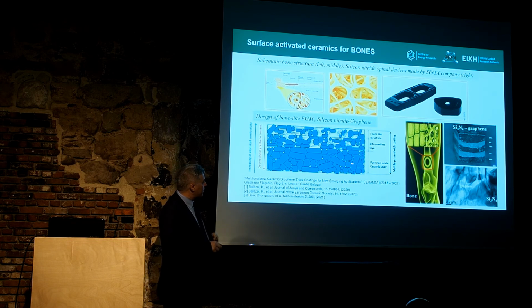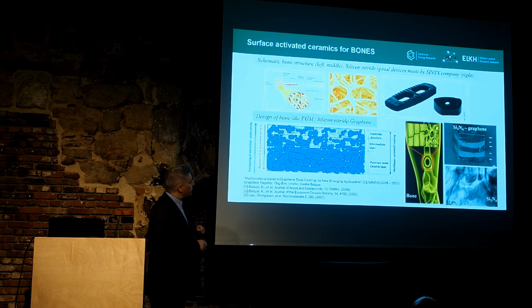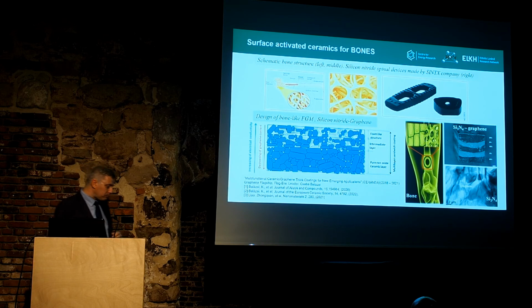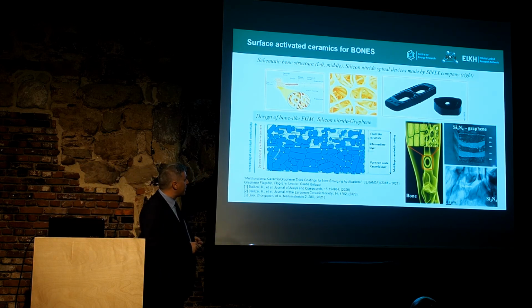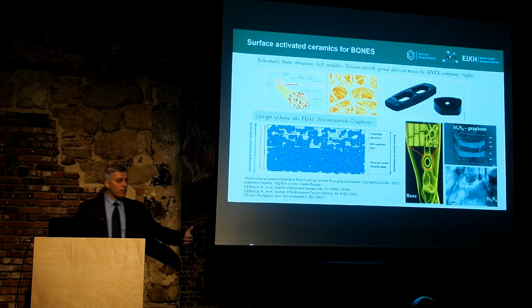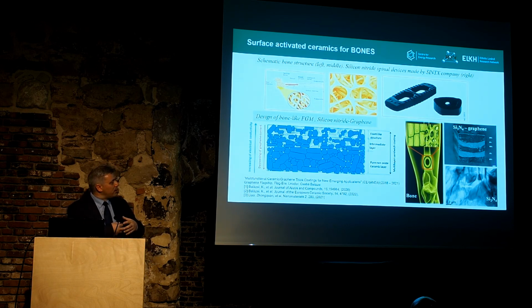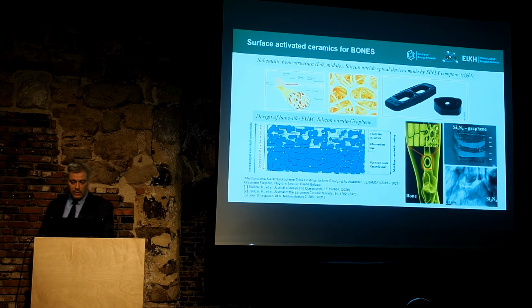So we have a dense, multilayer structure. We incorporated graphene in an individual part, and we make a foam-like or porous structure. Actually, it is like trabecular bone, so porous bone. By incorporating graphene we could increase not only the porosity, but we also provided electrical conductivity to the structures. We also know that bone cells can be made to spread more easily by applying electrical current, so we can initiate the spreading of the bone cells. In our case, the bone cells should be attached very strongly to the surfaces, and we should produce new bone by using hydroxyapatite, which we are using.